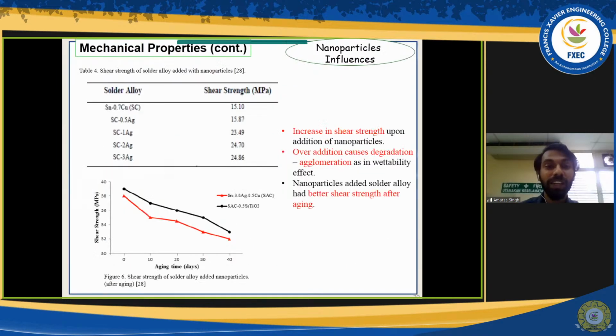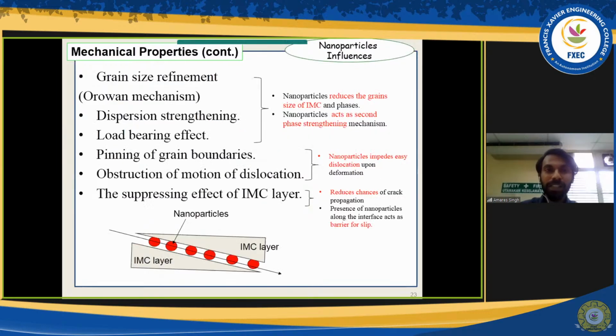Likewise, for the shear strength, we try to add more percentage of nanoparticles. If you have a small amount of weight percentage, it gives us better shear strength compared to a higher amount of weight percentage addition. This is again due to the agglomeration and also the grain refinement of the microstructure and of the thin IMC layer. So these are a few gathered mechanisms said to be the reason for the increase in the shear strength and also hardness.